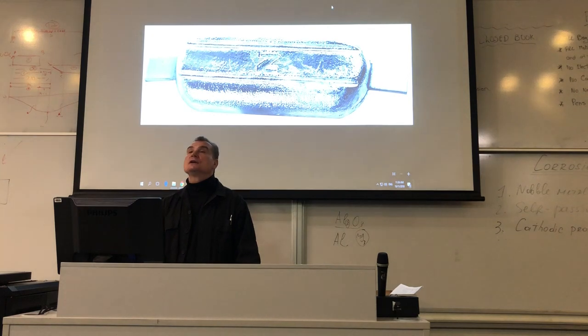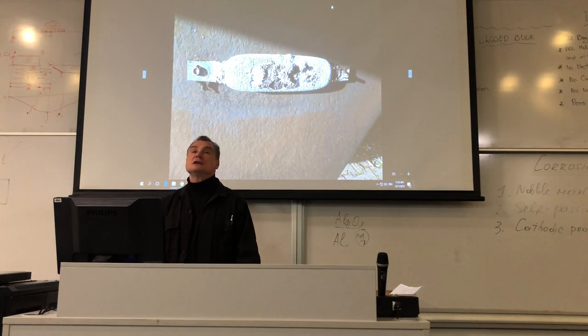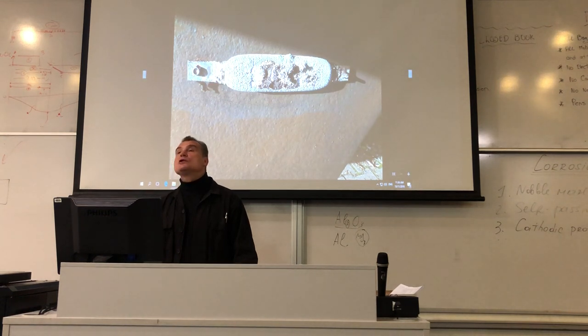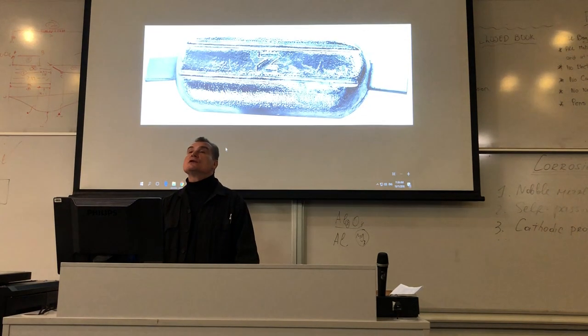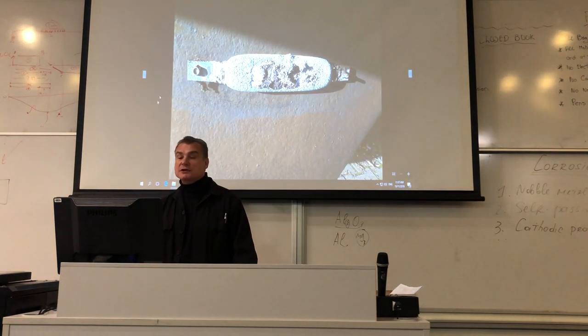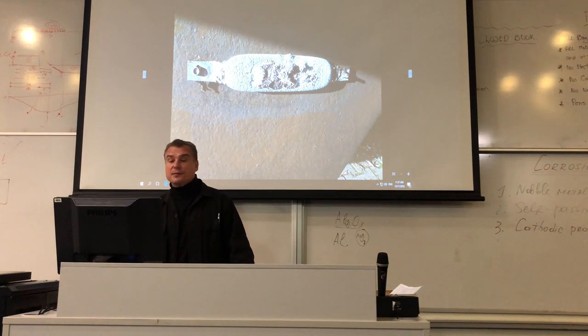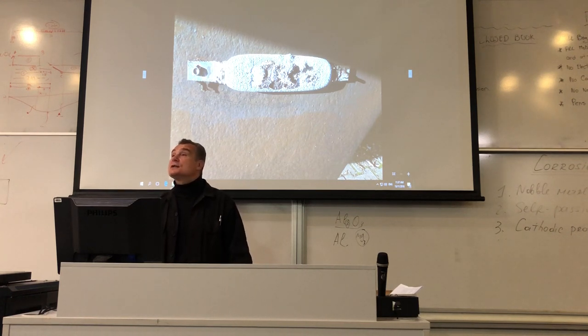This is how the new anode looks like, and this is how the old or used one looks — that one in service is almost gone. What do we need for that anode to work? We need a strong connection between the metal and the zinc. We need to make sure the connection is not corroding or disconnecting. If there is no connection, those electrons would not be able to travel, and our anode is going to be useless.